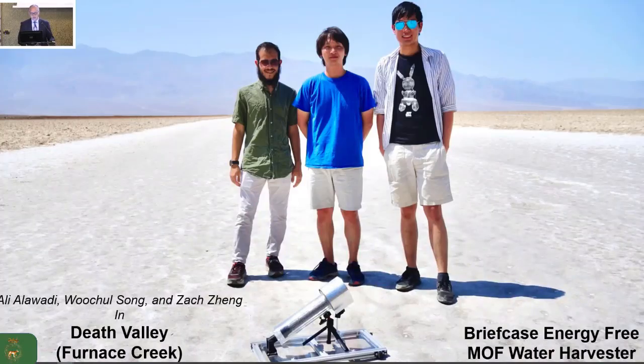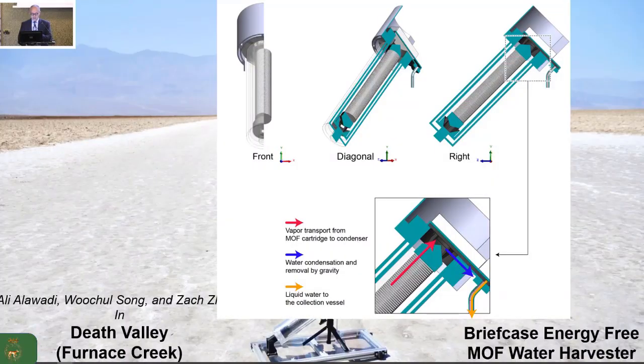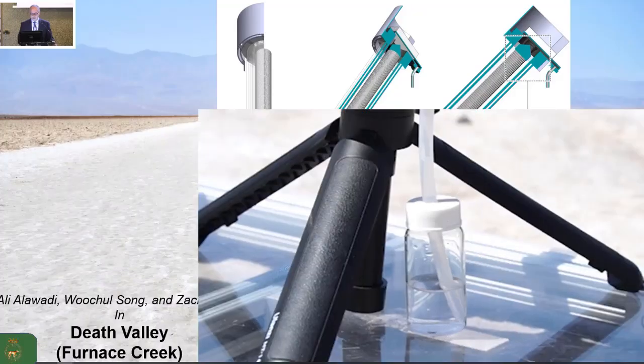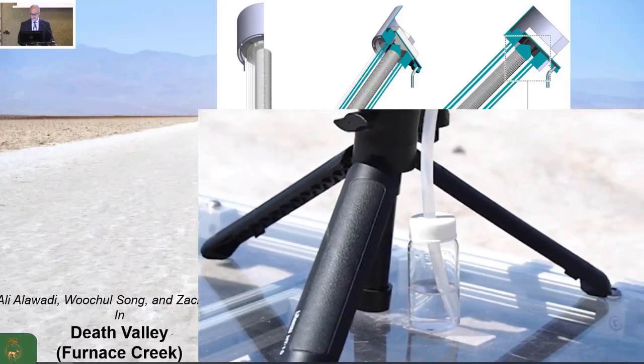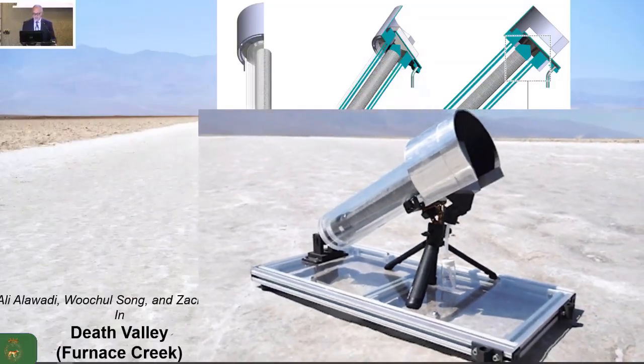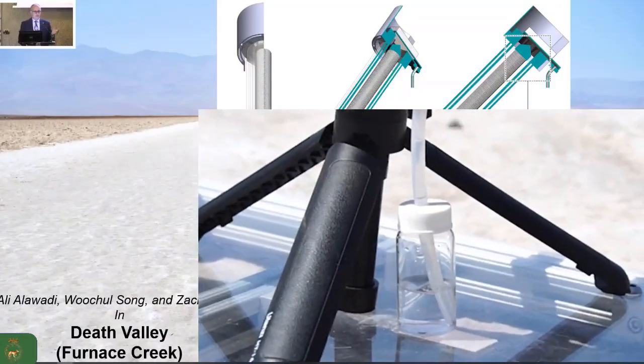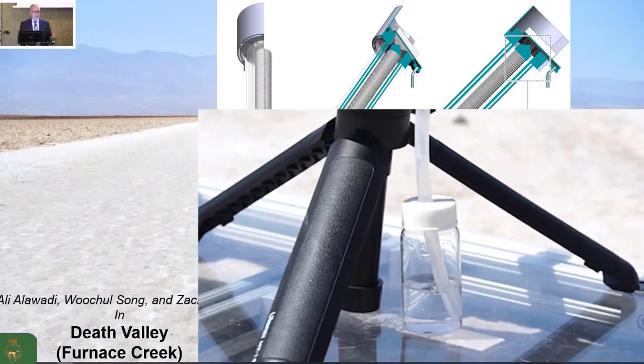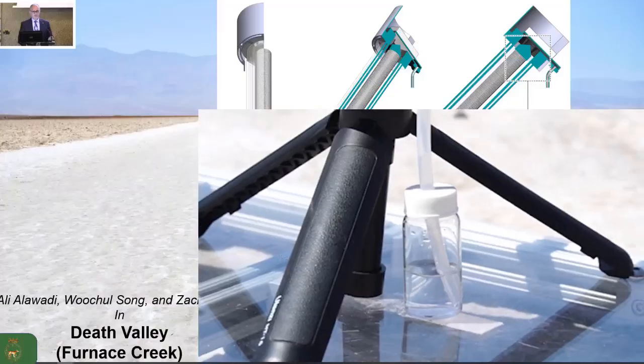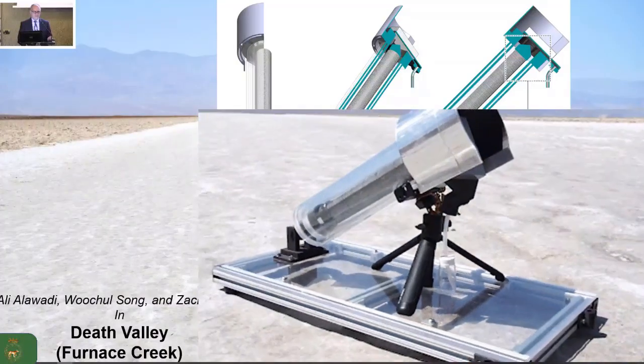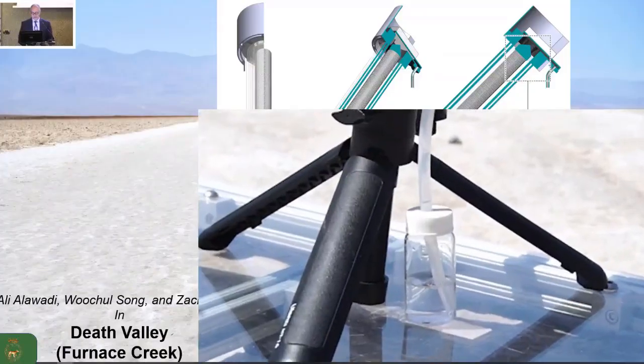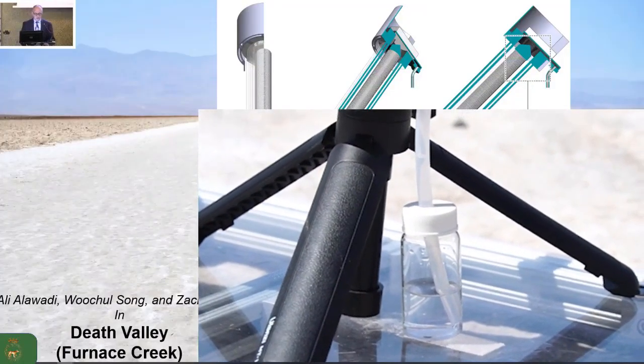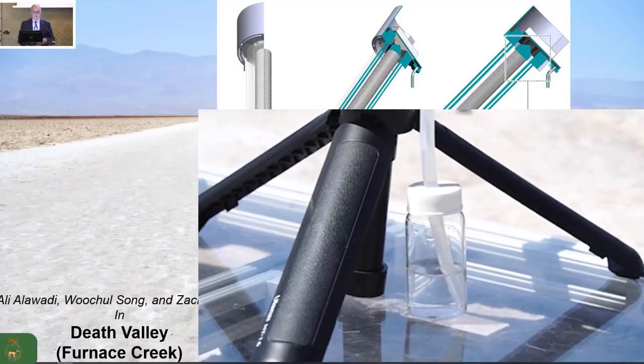So the students took this to the desert and showed that, in fact, you could make a device that is pancakes of MOF, and when exposed to air, it takes up water from air, and during the day, when it's hot, you put it under sunlight, and it generates water. Okay? There is no energy input aside from ambient sunlight, and it's pure, ultra pure water. This is the most clean water you'll ever find, because the MOF is a filter in itself on the microscopic level, and the components of the MOF don't leach because of the strong bonds holding them together.